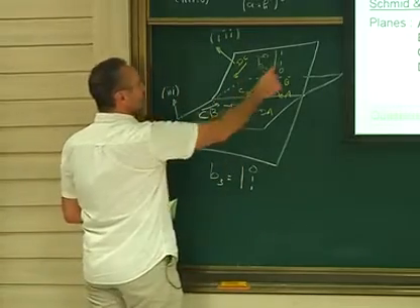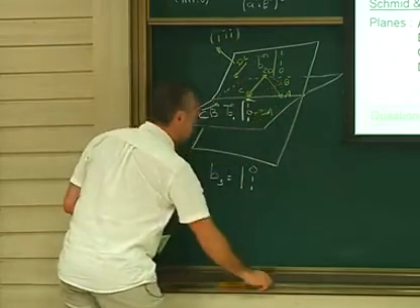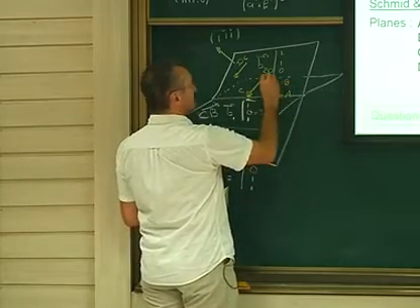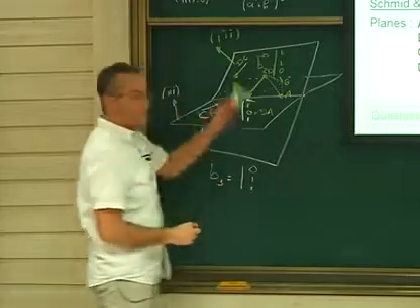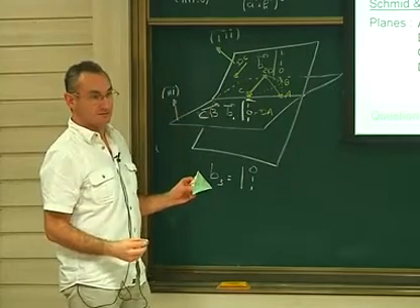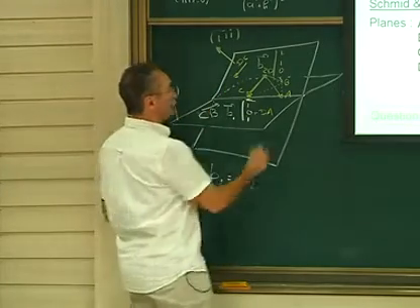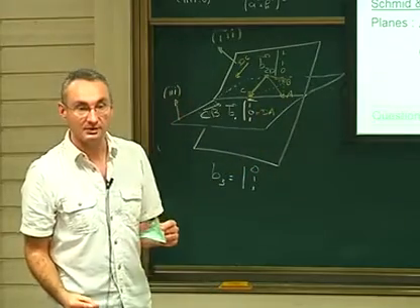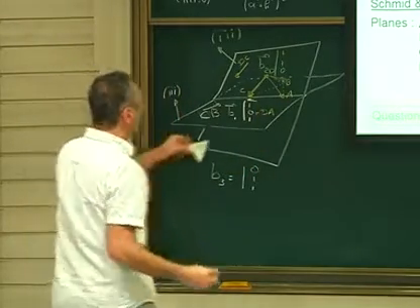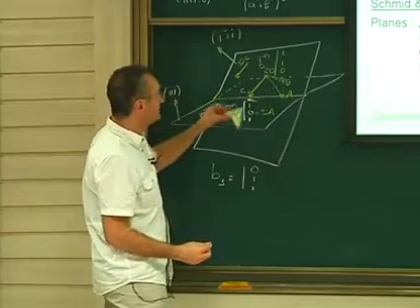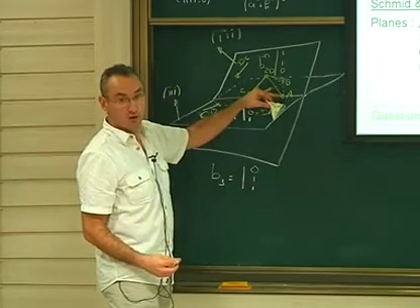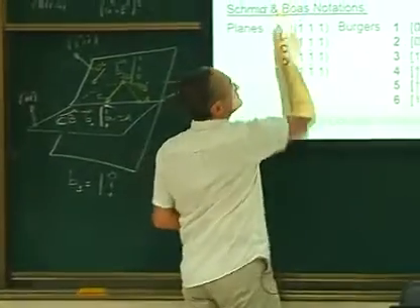So what could it give? DC plus CB. What is the reaction? DC plus CB will be DB. And how is the DB vector compared to the two planes? It's out of the plane. So this will create a stair-rod if we took the splitting as we saw this morning, yes, indeed. And this is the Lomer-Cottrell lock. The Lomer-Cottrell happened here, typically what we saw this morning, okay?